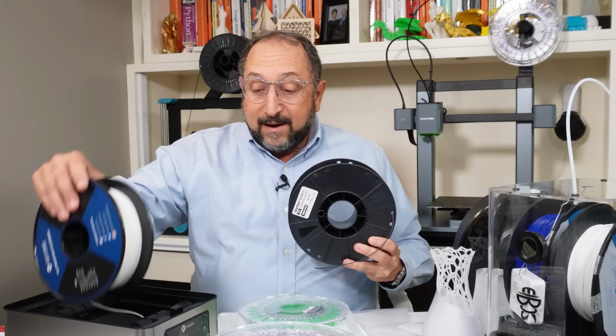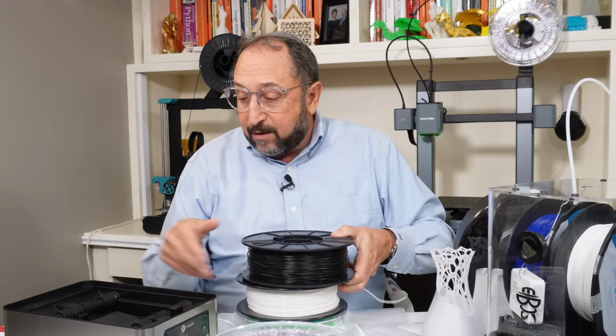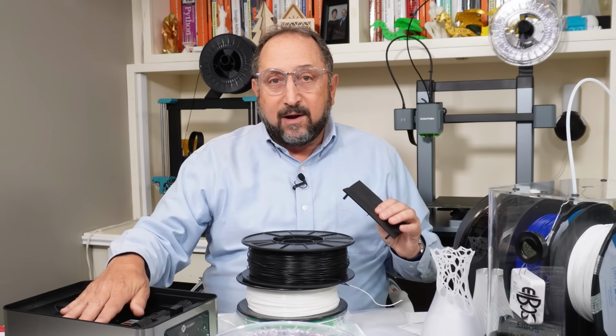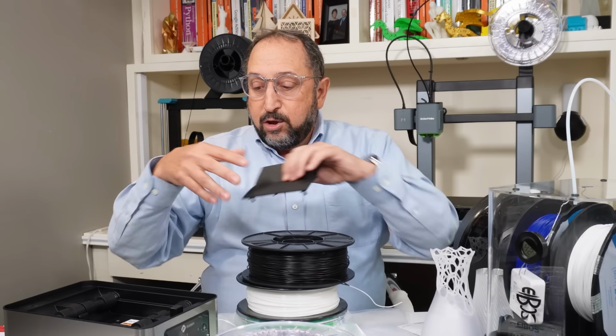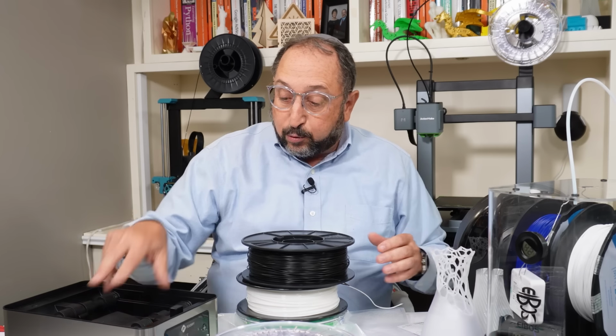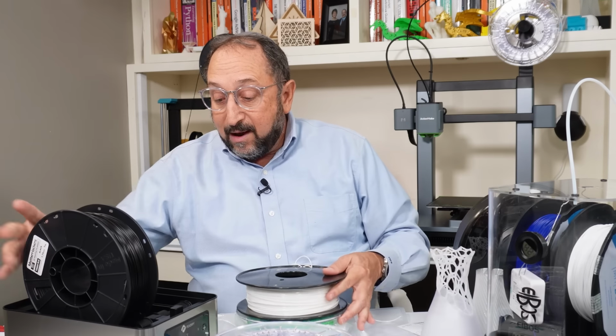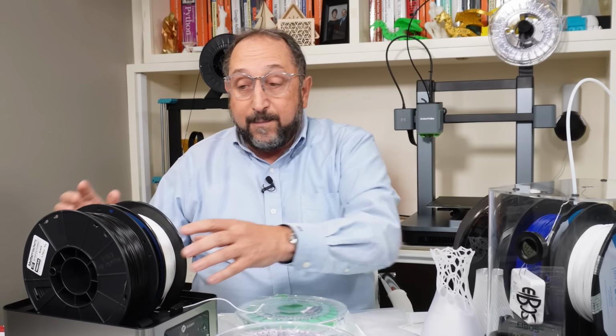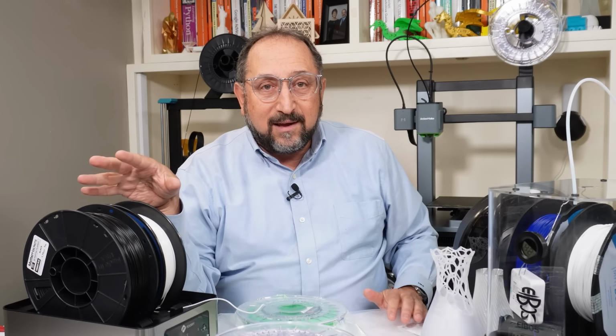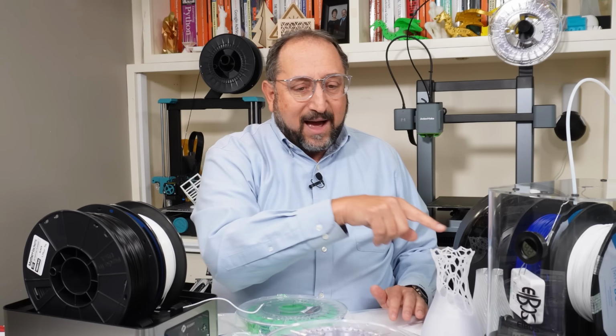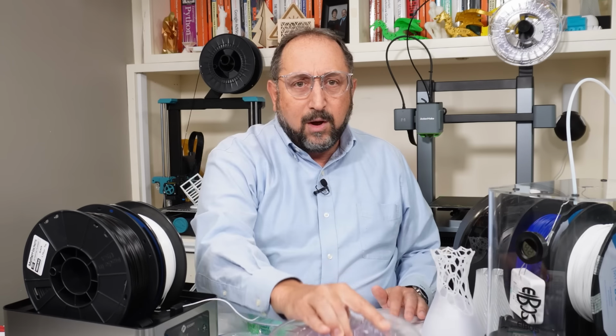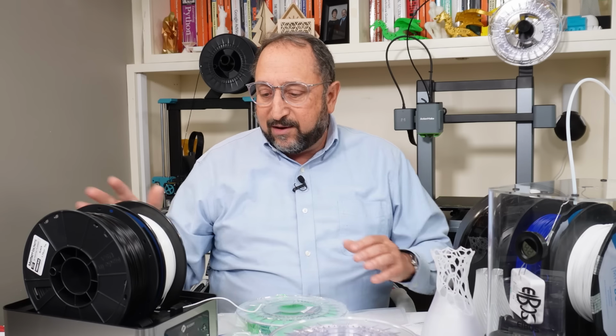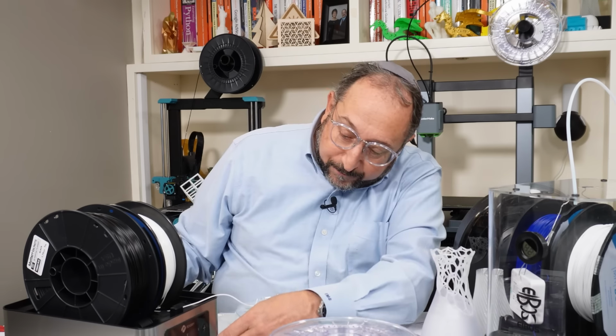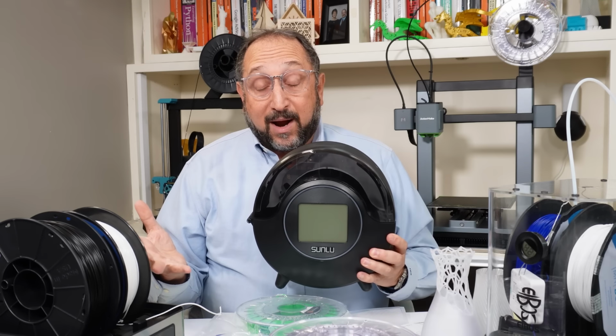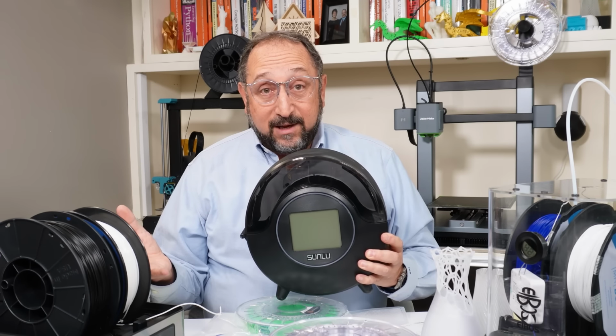And they have an interesting feature here. They have a little deflector that they recommend you use when you're not printing directly from this device to keep the hot air from hitting the reels directly. And it might have been that the hot air directly hitting this reel was why the 70 degrees Celsius impacted this print. All three of these print dryers work effectively.